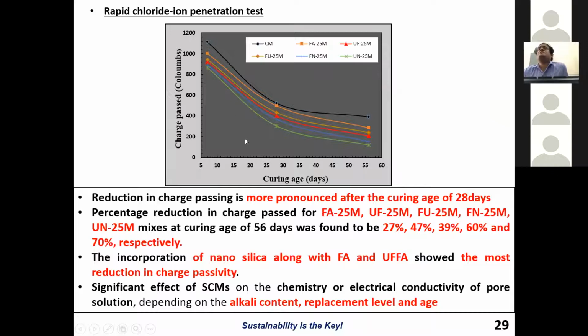And these are the values for the rapid chloride ion penetration test. This curve depicts the curing versus the charge passed in coulombs. It is similar to porosity, because it represents how many pores there are in the concrete. So it is presented in a similar way to permeable porosity. The mixes having nanoparticles are quite a bit lower compared to other mixes.